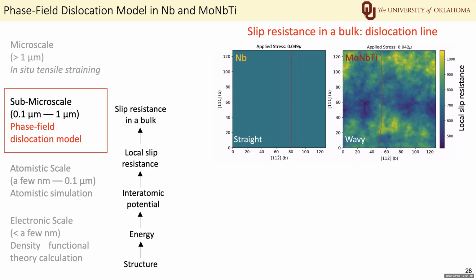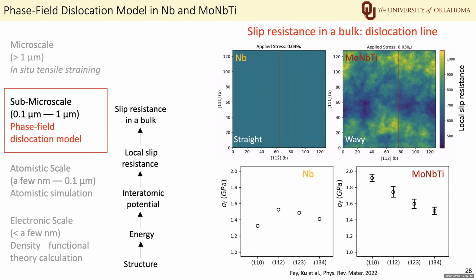The dislocations are initially straight, and in niobium it remains straight when gliding. However, in molybdenum niobium titanium, the dislocation becomes wavy. That is because each point along the dislocation line experiences a different local slip resistance. We further find that the slip resistance in the alloy is higher than that in pure niobium. This suggests that the alloy is stronger than the pure metal.